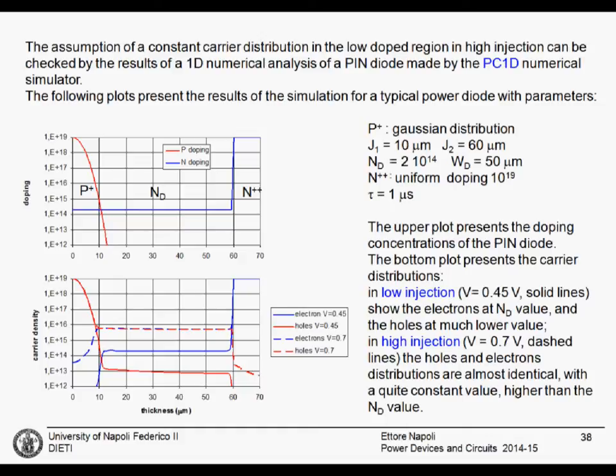These are the plots that present the results of the simulation for a typical power diode. The parameters of the diode are these. We have a P plus diffused anode that has a Gaussian distribution. The peak carrier concentration is 10 to 19, and the thickness is 10 micron. The junction is here. The other junction is at 60 micron, leaving 50 microns for the N layer.